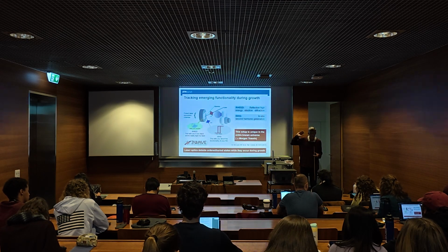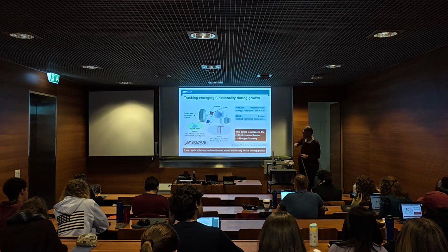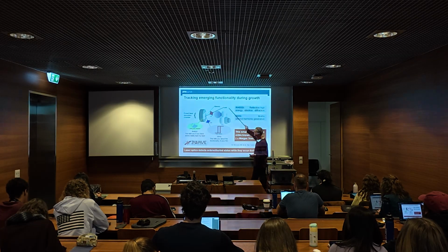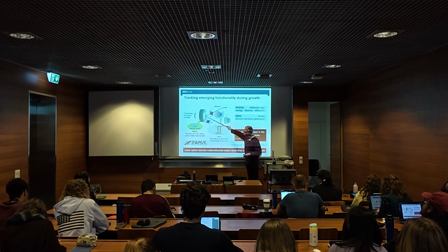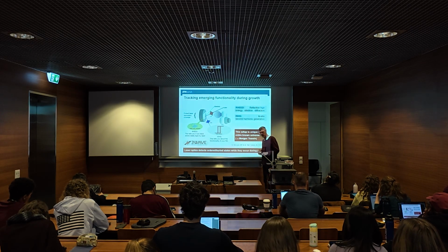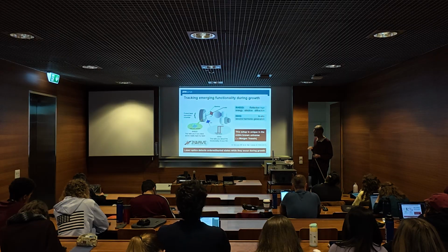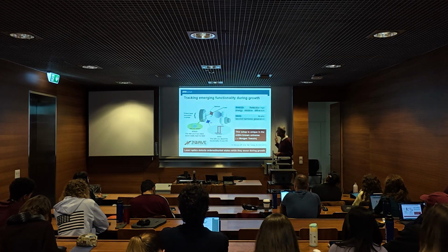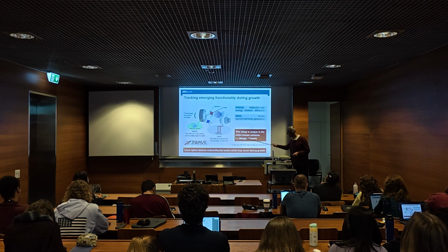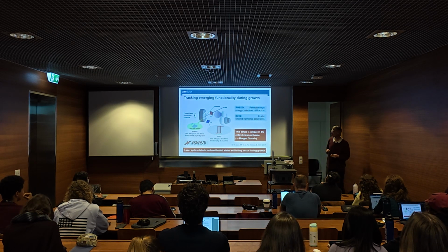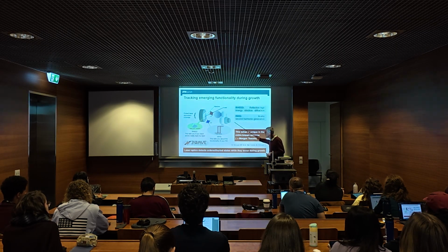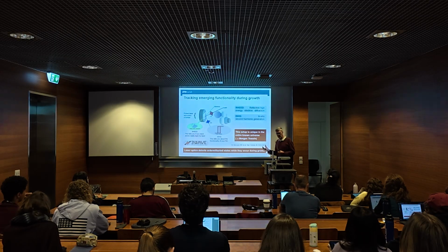Now remember, ferroelectricity breaks inversion symmetry and switches on this light conversion. So that's what you do. You send a laser beam onto your target, onto your film while you grow it. You measure the frequency-doubled intensity, and when it is there, you know, oh, my film gets ferroelectric. So that's something that you can do, and we have the setup, and it's basically the only one you find on this planet, and therefore in the universe, to monitor thin film properties emerge while you grow.